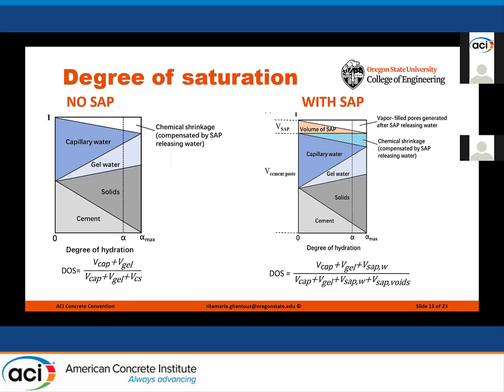Now, to pass on the degree of saturation calculation, how we did do these values. These were performed based on Powers model for all the cement mixtures tested in the study. The schematic presentation on the left of this slide represents the volumetric phase volumes of cement-based sample without SAP addition, while the one on the right represents the volumetric phase change for cement-based sample with SAP.